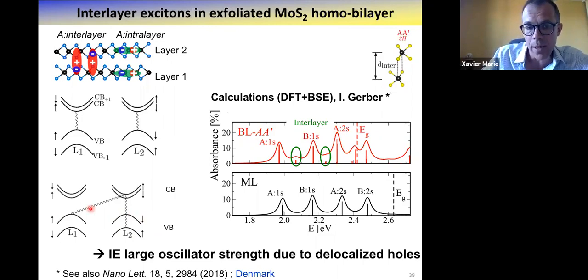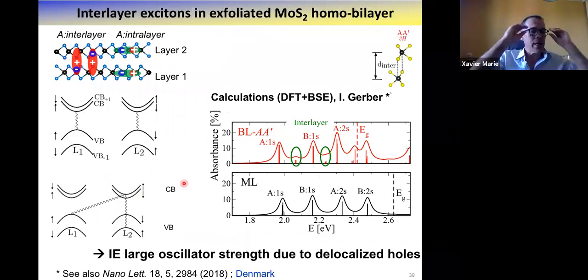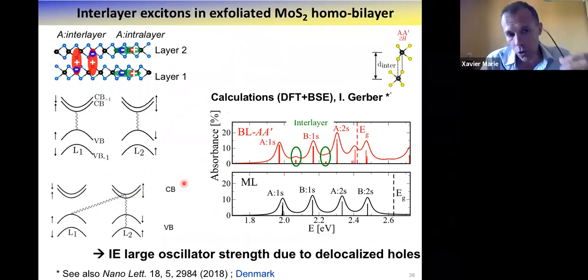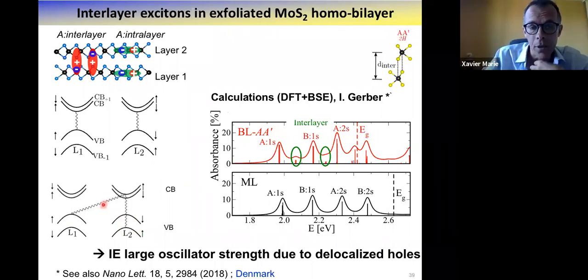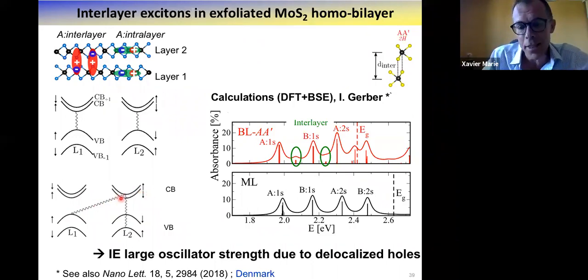You will have a hybridization of the hole state, whereas for the electron, the interlayer coupling due to this dz square orbital vanishes. Whereas for the hole, it is allowed. And so when we speak about interlayer exciton, in fact, you have to consider that the interlayer exciton has an intralayer component because of this hole tunneling or delocalized hole.